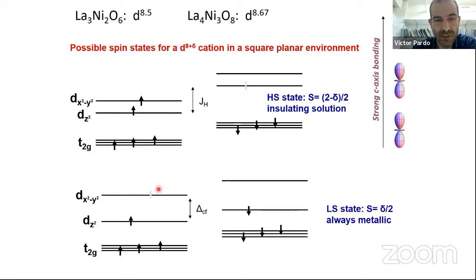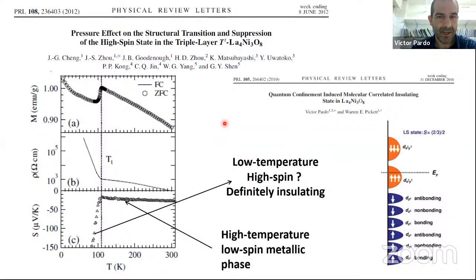This low spin solution would be interesting because it would have the dx squared minus y squared band at the Fermi level. This would be partly filled, and this would be a metal. However, this high spin state solution would have the dz squared electrons at the Fermi level, and this could suffer bonding, antibonding splitting, leading to an insulating solution, which is what you don't want if you're looking for superconductors. So we need to understand how these two phases compete. And what we saw, as I said before, when you have the low spin state solution, you have a metal, you have a representation like this.